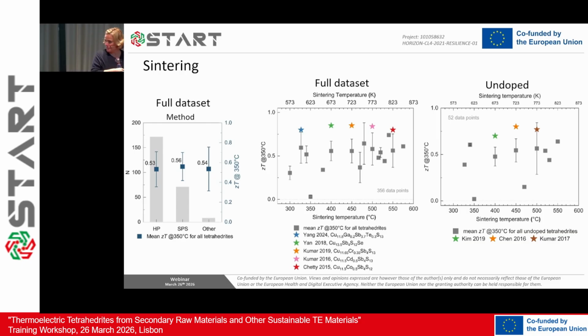We decreased until 340. But what you see when you plot, which again is very strange, is no matter the temperature on average, and these are the peak values, so these little stars are star data, they're really good, they're the best for this class. You see that not only does the average change, again a lot of dispersion, but also the best doesn't change. Different compositions, again we are not normalizing, the compositions are all mixed. But there doesn't seem to be a very important contribution from the sintering temperature, which is really, really strange.